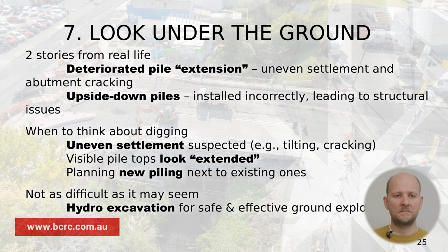Everyone suspected, oh, probably the engineer did something wrong, and they didn't take into account the existing supports. But in fact, once we dug down, we found there was no pile underneath this section, which was very strange. We did find a pile about 1 meter deep. What appeared to happen is that quite often the piles could be driven slightly deeper than you expect, and the contractor at that time seemed to extend this pile with side concrete, which wasn't as durable. So this concrete almost completely deteriorated, leaving no support, no steel and no connection to the abutment, causing this part obviously to move as soon as we gave it space to move.